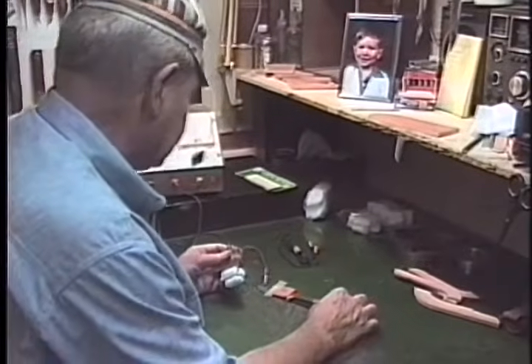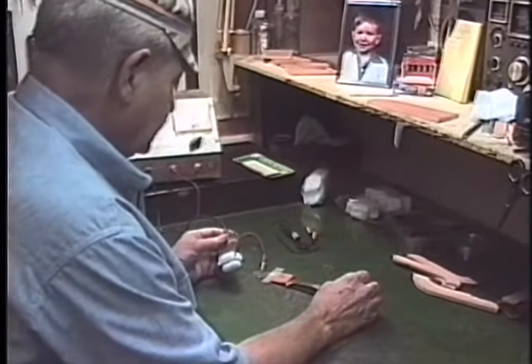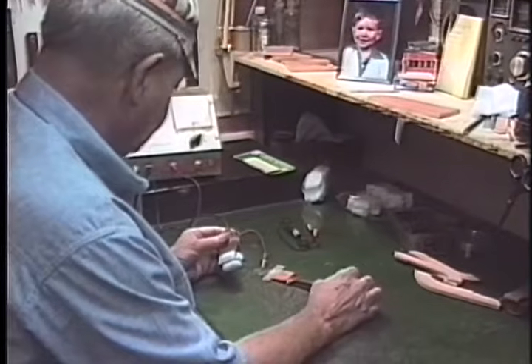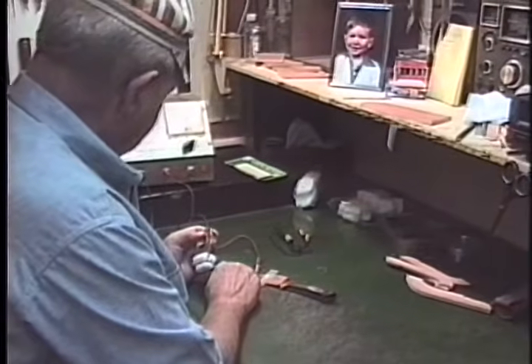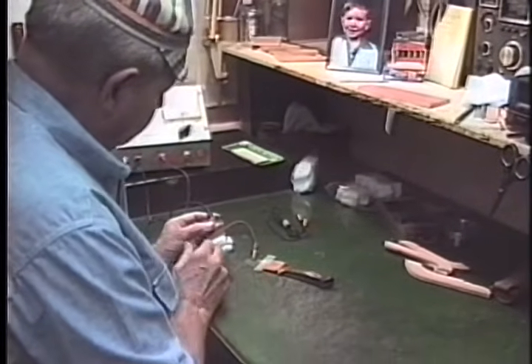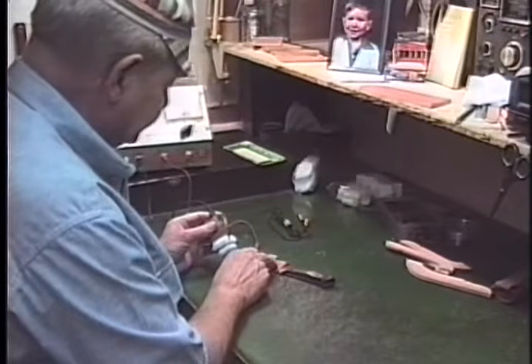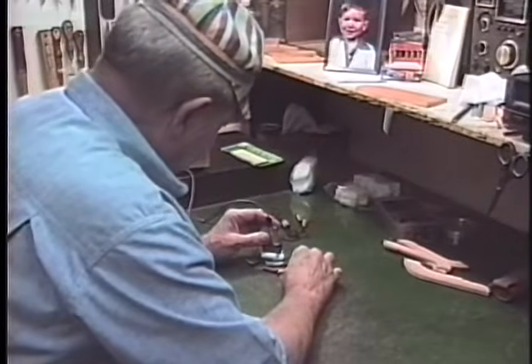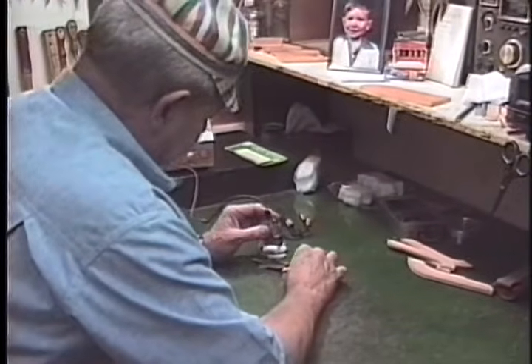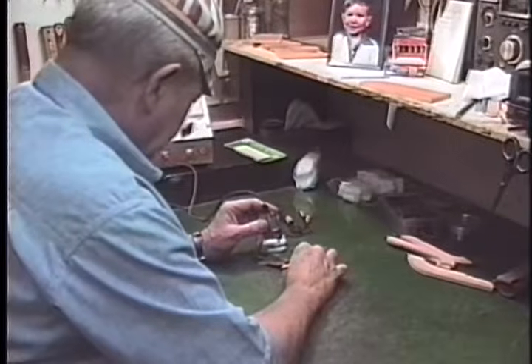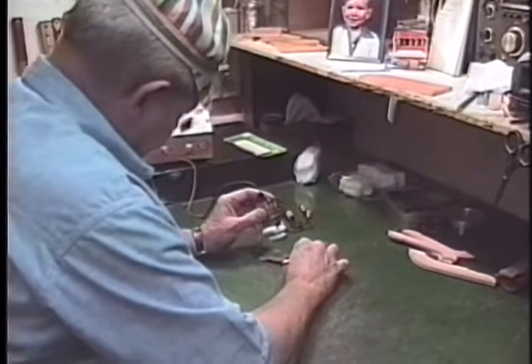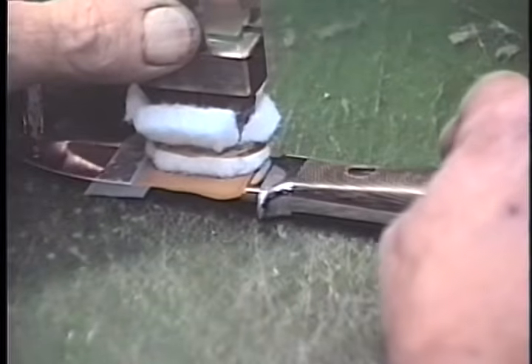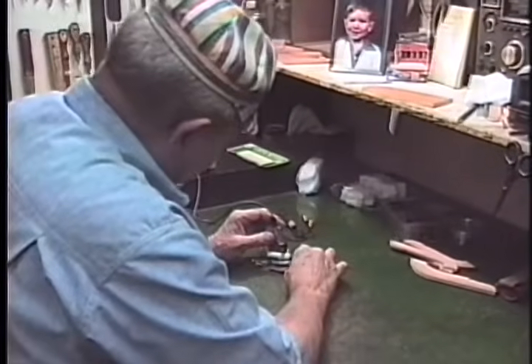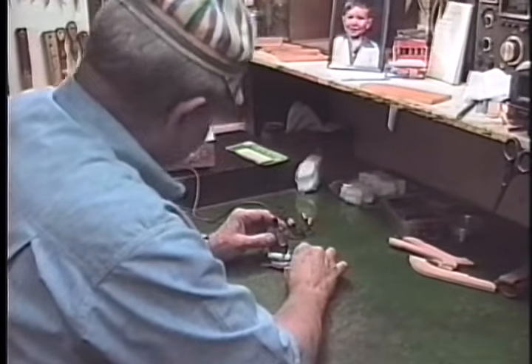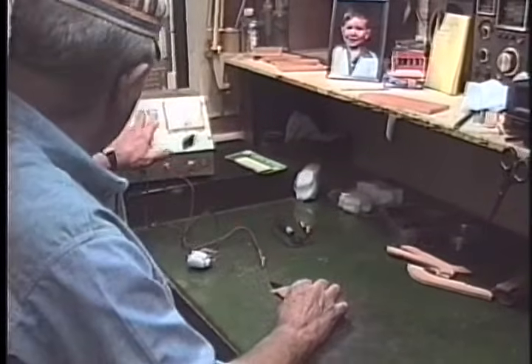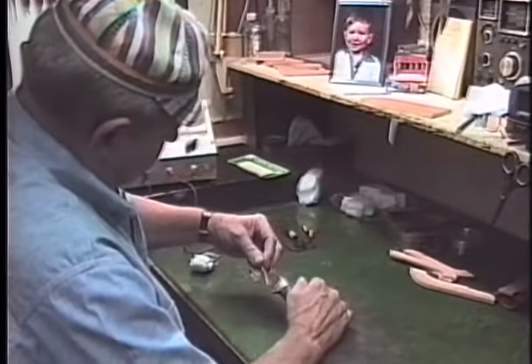Well, we got this knife all finished, and the last thing we do is we want to put a trademark on it. And this is the way we do it. We got the machine hooked up. The ground wire goes to the blade. The power wire goes to this stencil holder with a wet cotton surface, and we got the stencil taped onto the blade. We go down on this for about a second or two, come off and let it degas. Another couple of seconds and degas. We do that 4 times. Each time we're burning it deeper. Then we reverse polarity from DC to AC, and that will darken the bottom of the etch. About 3 or 4 seconds, take it off, unclip the ground, and now we have a trademark.